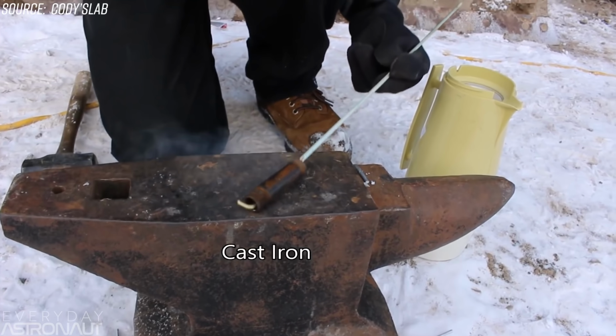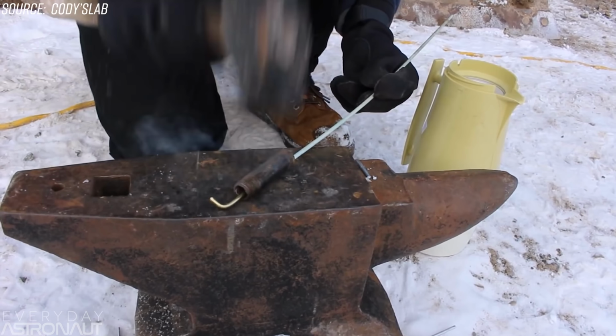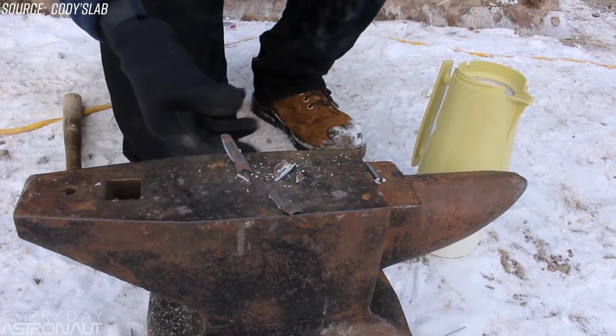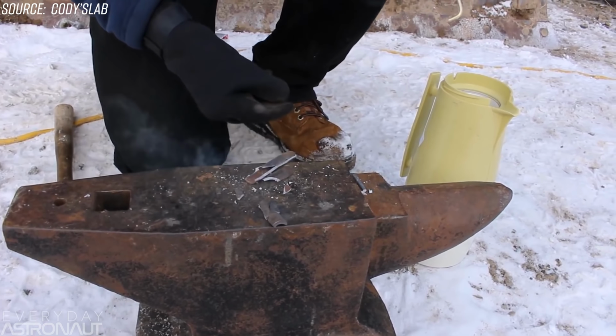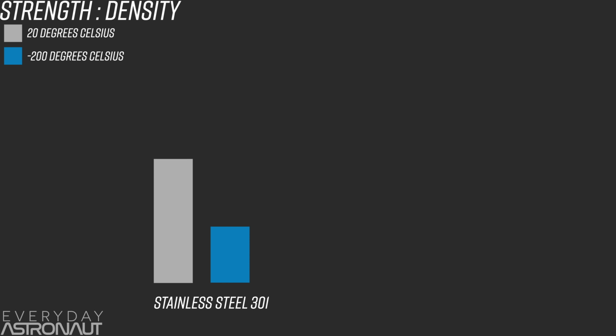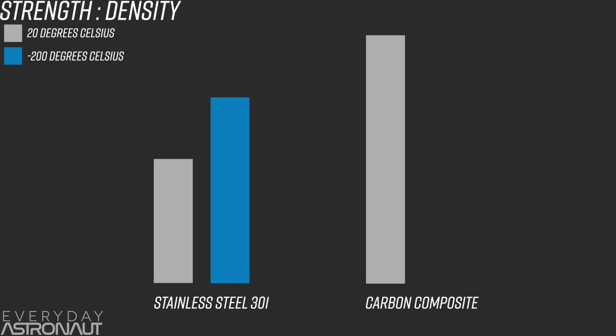Most steels become brittle at cryogenic temperatures. Perhaps you've seen videos like this one from Cody's Lab of someone taking metal, chilling it with liquid nitrogen, and smacking it with a hammer. Many metals become so brittle at cryogenic temperatures that they're basically useless. But stainless steel with a high chrome nickel content like stainless steel 301, at cryogenic temperatures, its strength is actually increased by 50%. And that's in pretty sharp contrast to carbon composites, which become less strong at these temperatures.